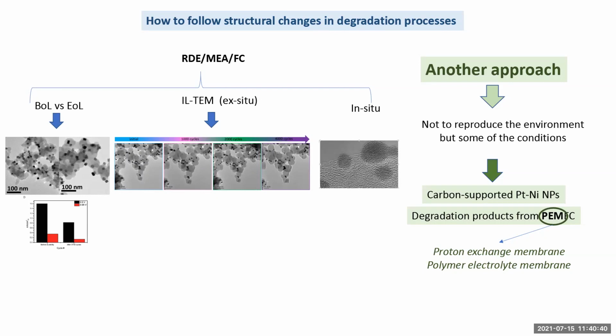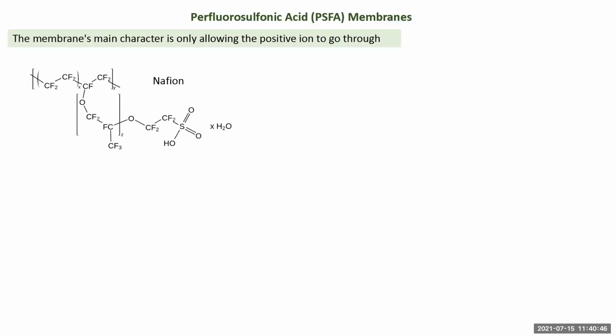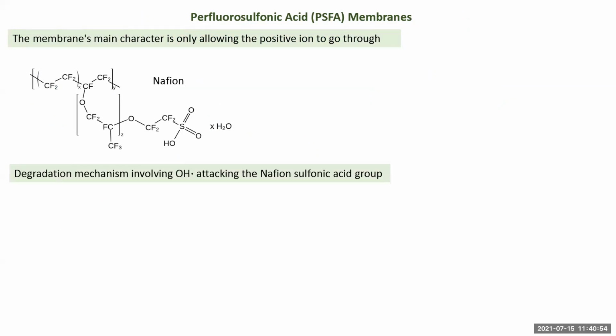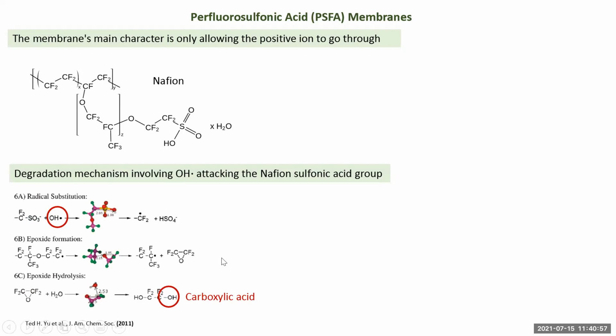Not only does the catalyst degrade, but all the components of the fuel cell usually degrade after use. So this is the Nafion membrane, the most commonly used, or if it's not Nafion, it's from the family of Nafion. And the degradation products usually are carboxylic acids. These carboxylic acids are the products of radical substitution. And we have a lot of radicals inside the fuel cell, because nickel, the second metal in the catalyst, activates the formation of peroxide. So it is very common to have carboxylic acid inside.